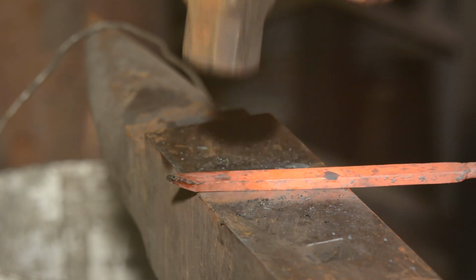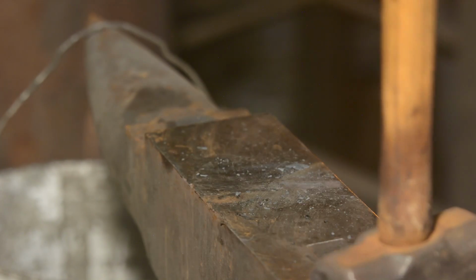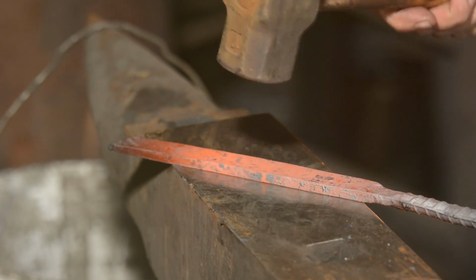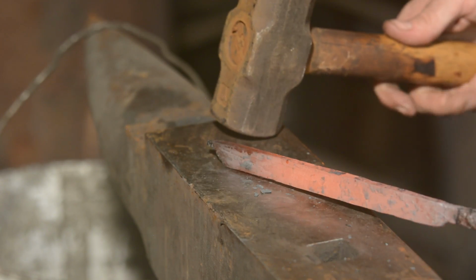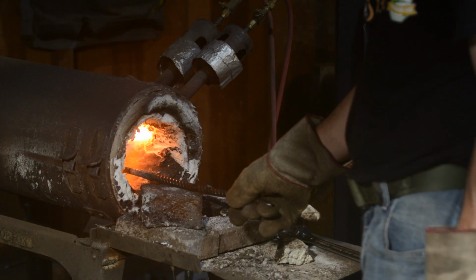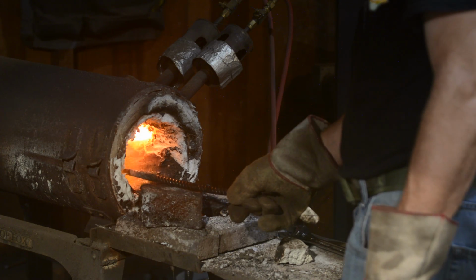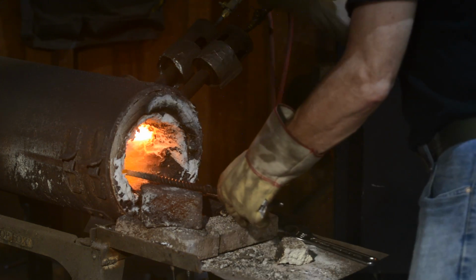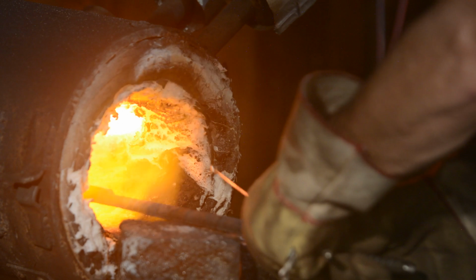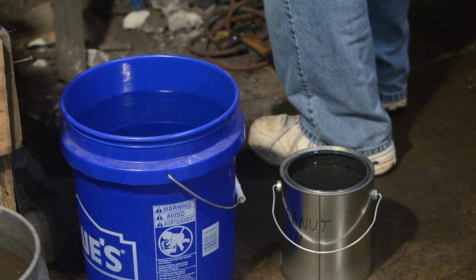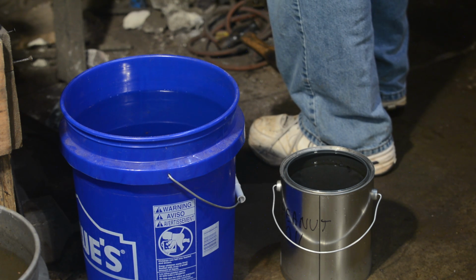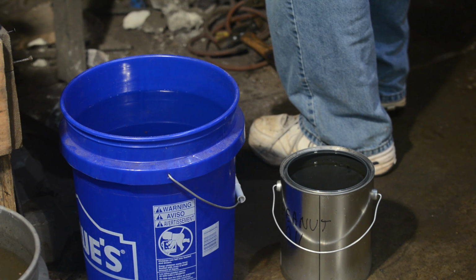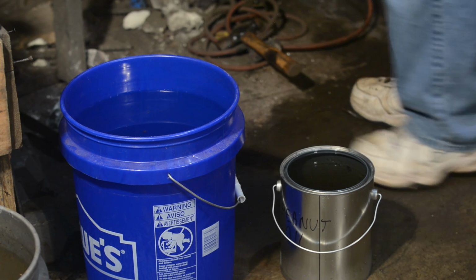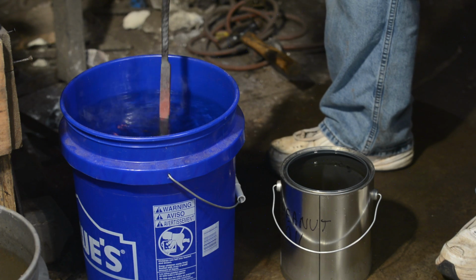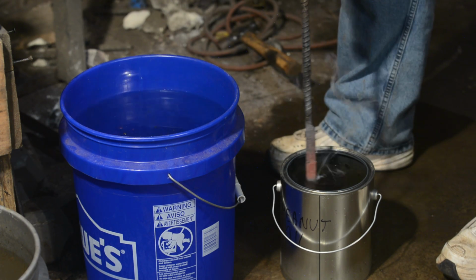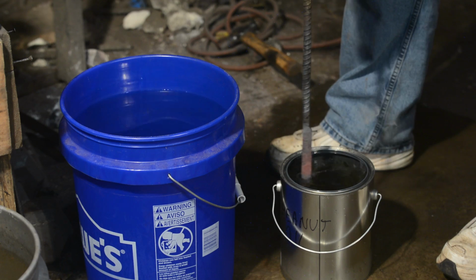So with normal knives, I'd rough out the shape of the blade on the grinder before heat treat, but not in this case. There's just not that much else to do, so I'm going to do it all in one throw. Instead, I'll immediately heat treat it by heating it to about 1500 Fahrenheit and quenching it. I use a two-stage quench. Into water for about 2 seconds to get the steel past the pearlite nose of the cooling curve, then into oil to bring it on down to martensite transformation a little bit more gently. This gets the steel nice and hard, but helps to minimize the likelihood of cracking, which often happens in a straight water quench.